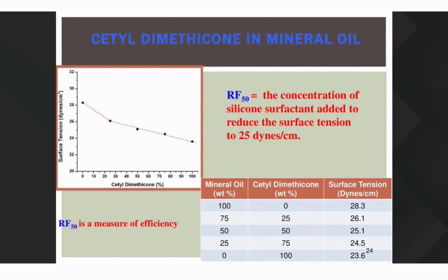The same material, when you put it in mineral oil, you get a lowering of surface tension, but where's the inflection point for the CMC? You really don't see it. So that's why we're calling it RF50. What's the percentage you need to get the surface tension at 25? And then you can compare the efficiency of how these things work in your formulas.